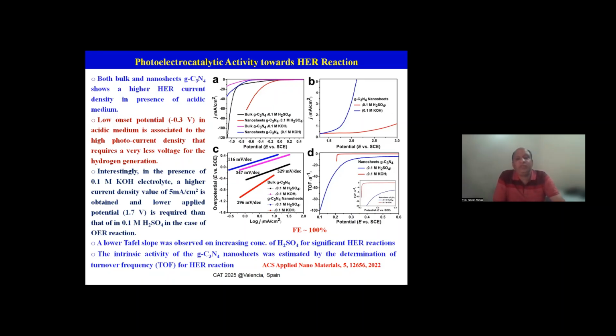So now these materials could be used for photoelectrocatalytic activity towards the HER reaction. Here you could see the LSV plot for the HER, and then the LSV plot for OER. The downside plots belong to the Tafel slope plot, and the last one is the turnover frequency plot. These investigations suggest that a high HER current density in the presence of acidic medium could be observed, and the low onset potential in the acidic media suggests a high photocurrent density that requires less voltage for hydrogen evolution, and the low value of the Tafel slope shows the significant HER reaction. The intrinsic activity of graphite carbon nitride nanosheets was estimated for the determination of turnover frequency for HER.